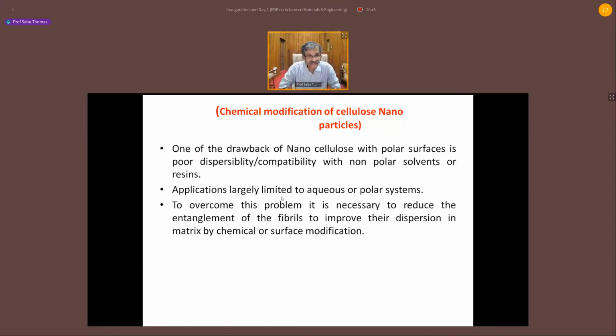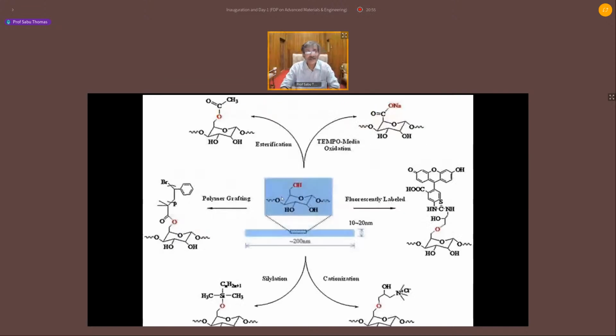Therefore, in order to overcome these incompatibility issues, in order to overcome the dispersion issues, especially with the non-polar polymers, one has to do surface chemistry. Because look at the structure of this material. We have fantastic hydroxyl groups. So you can do TEMPO oxidation. The OH could be converted into COOH. You can do esterification reaction. You can do polymer grafting. Polymers could be grafted on the surface of nanocellulose.